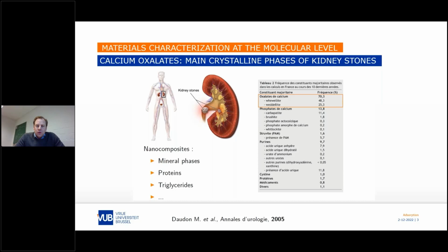From the calcium oxalates, there are two or three types that can be found in the kidneys: the mono, the di, and also, to some extent, the trihydrate species. Next to these, calcium phosphates like apatite, like bone, can be formed. But then we have other polymorphs that can be formed with or without defects and substitution of cations. So the calcium can be substituted, or we can make vacancies, and we can have other structural defects formed in these minerals.